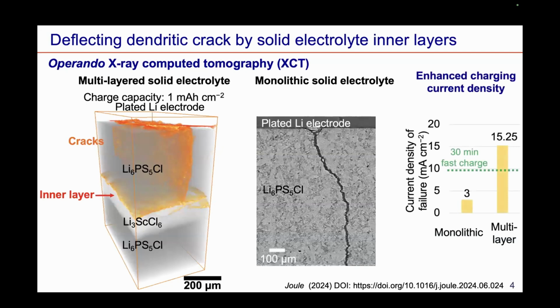So as a result, the batteries based on this monolithic electrolyte will be shorted under a current density of 3 milliampere per centimeter squared, which is far below the current density required for a 30-minute fast charging. In contrast, because of the dendrite deflection induced by the inner layer, solid-state batteries based on these multi-layer electrolytes will not be shorted under current density of 15 milliampere per centimeter squared, which will enable the fast charging.